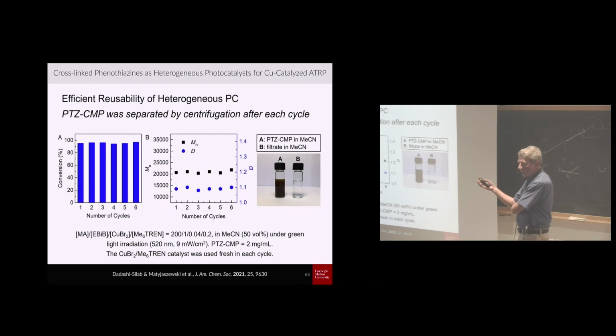So the last slide here shows really what happens if you isolate this system, because they are of a size, primary particles, maybe micron, but you typically have aggregated particles of tens of microns, so very easy to remove. You can just filter it in a simple way, and then run this reaction again and again and again, and same molecular weights, low dispersity, pretty decent control.